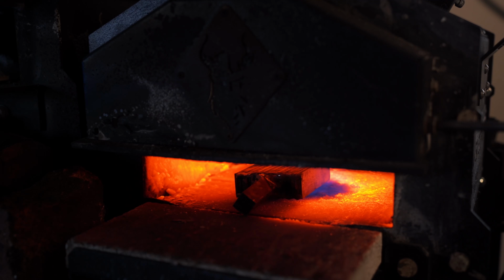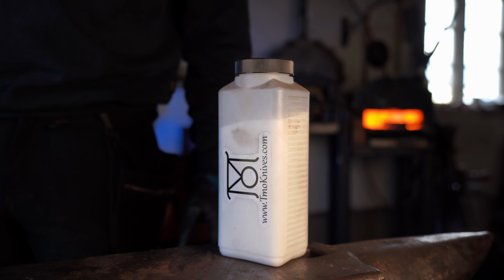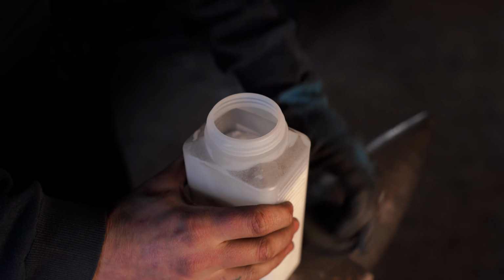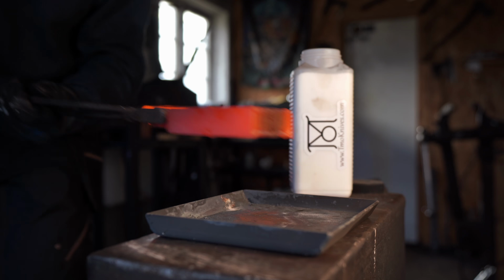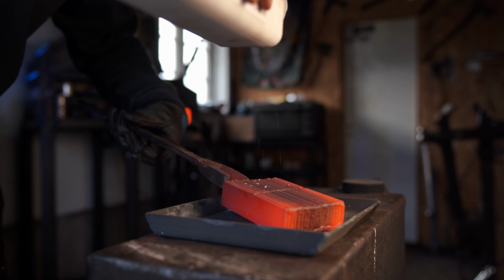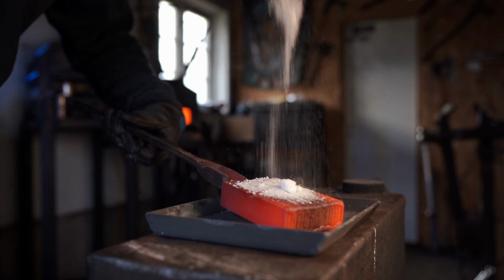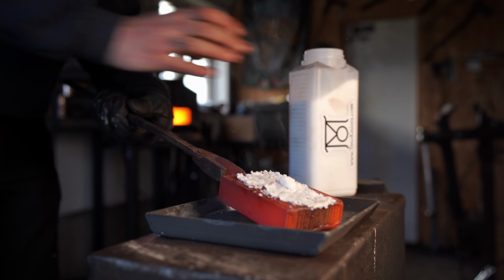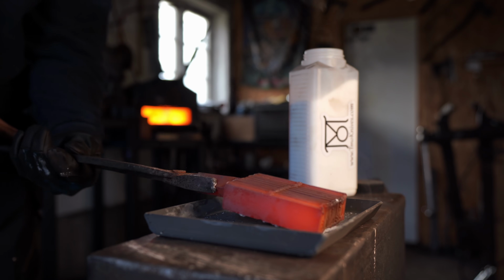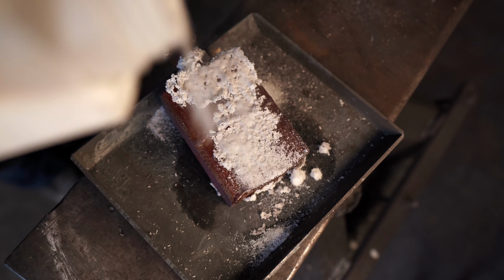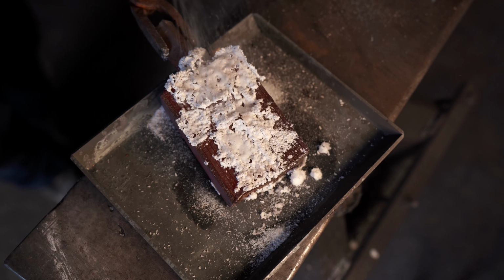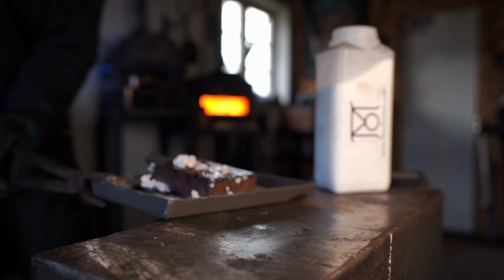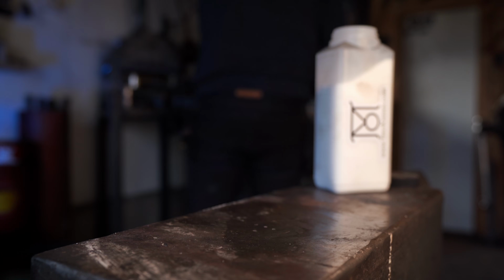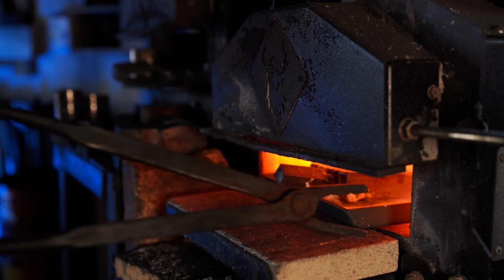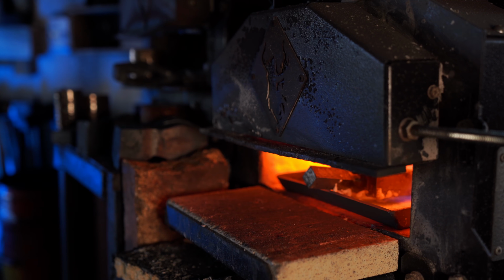Now before I heat it up to welding temperature, I take it out and apply some borax. Now this is probably one of the top 5 most commonly asked questions on my channel. What is that white powder? So borax melts at a high temperature and creates kind of a protective shield around the billet. You see, when hot steel comes in contact with oxygen, it tends to start forming scale, and that's the last thing you want when you're forge welding. You want the welding areas to be as clean as possible for a successful weld.